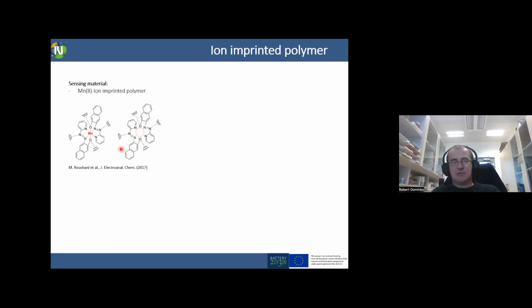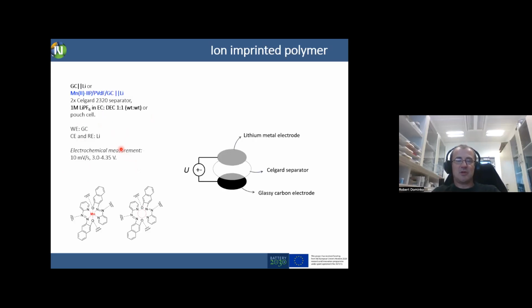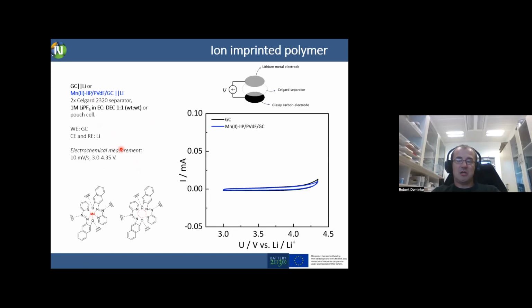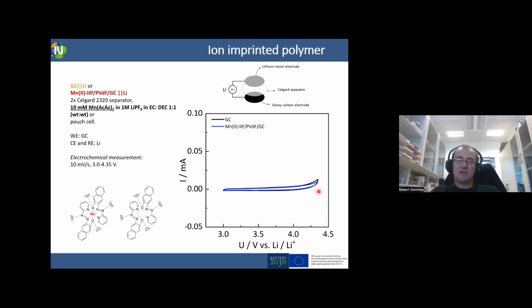It can also be used, we can imagine this polymer as a scavenger for manganese capturing, and that's another possible use of this polymer. And if we put this polymer in between the two electrodes and check whether it has some electrochemical activity in the voltage window where the battery operates, we see that there is this GC, which means glassy carbon, and that means that glassy carbon is covered with this imprinting polymer. We don't see any redox activity.